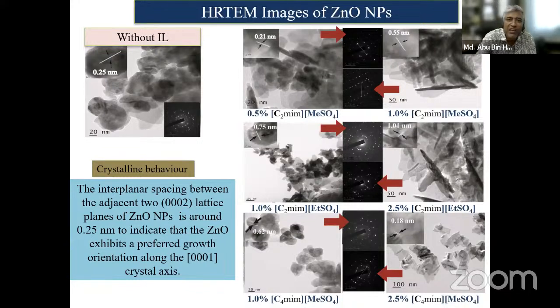Without ionic liquid and with ionic liquid, we have also checked the selected area electron diffraction, as well as TEM and HR-TEM studies, and the interplanar spacing between the adjacent (002) lattice planes of zinc oxide nanoparticles is around 0.25 nanometer, indicating that the zinc oxide exhibits a preferred growth orientation along the [0001] crystal axis. So we can have crystalline behavior, and please listen carefully, the growth can be controlled in a certain direction. This is actually very interesting. So we shall exploit these properties for use in the double salt ionic liquids.